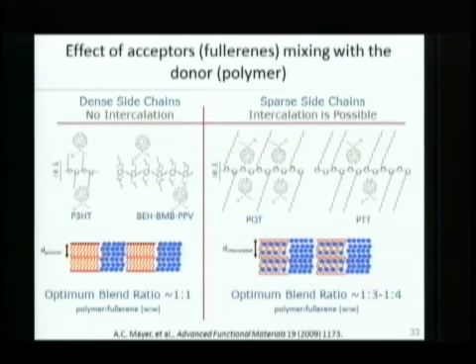On the other hand, if we use other polymers where the side chains are really close to each other, the fullerenes can't get in there, and then we'll have pure regions of polymer or donor and pure regions of acceptor. And normally we want about half the film to transport holes and half to transport electrons. And so then our optimal blend ratio is about 1:1.